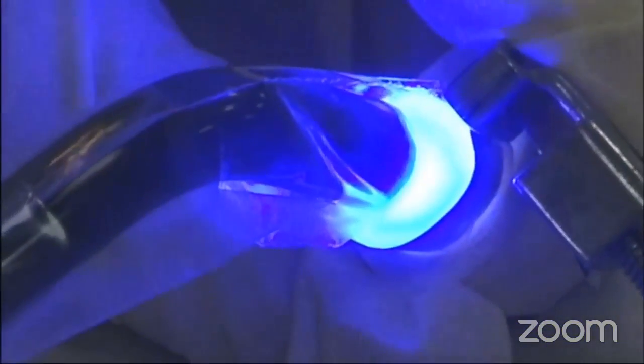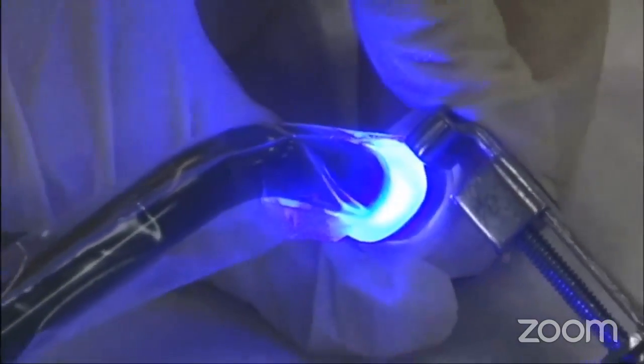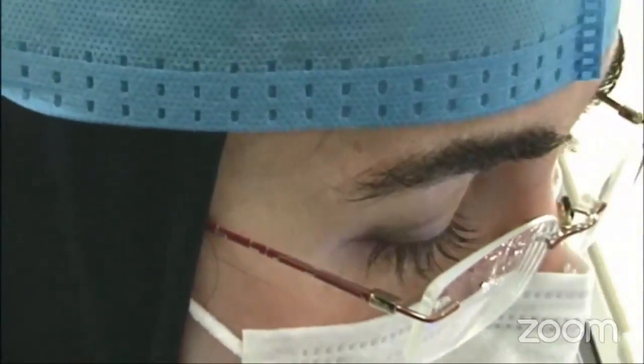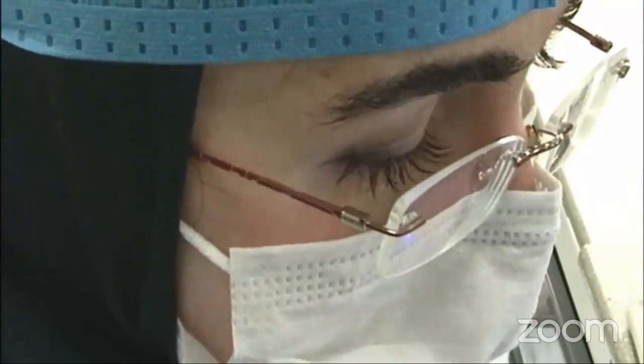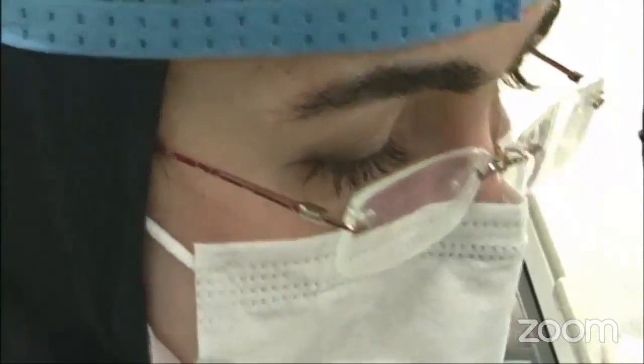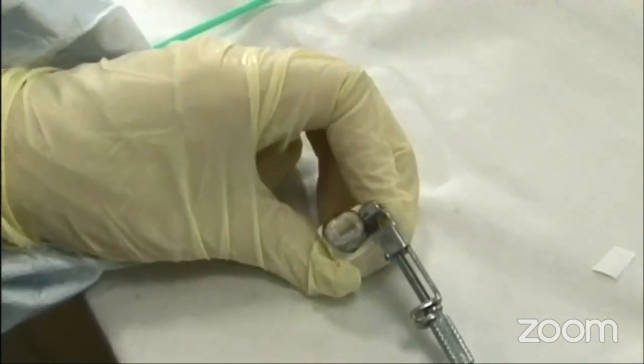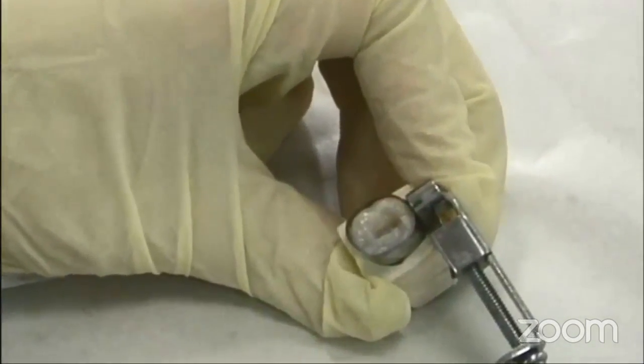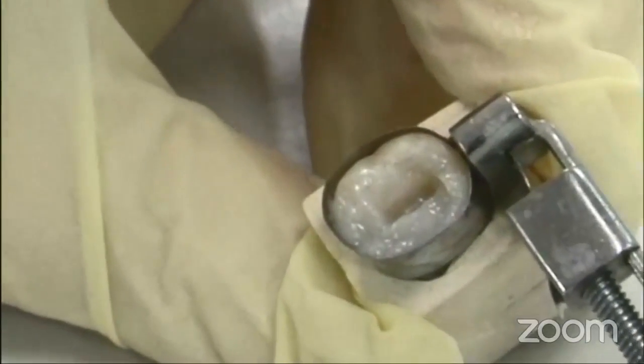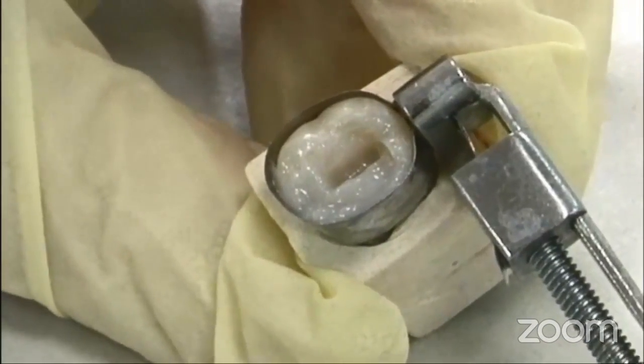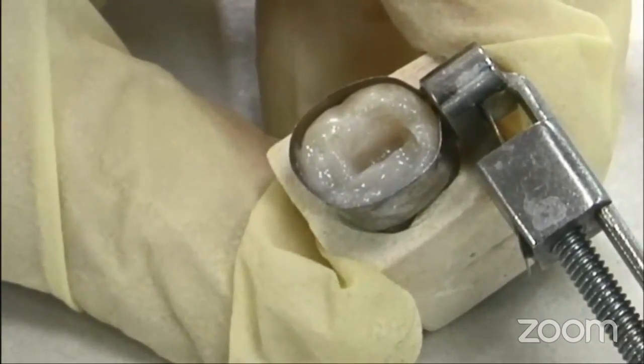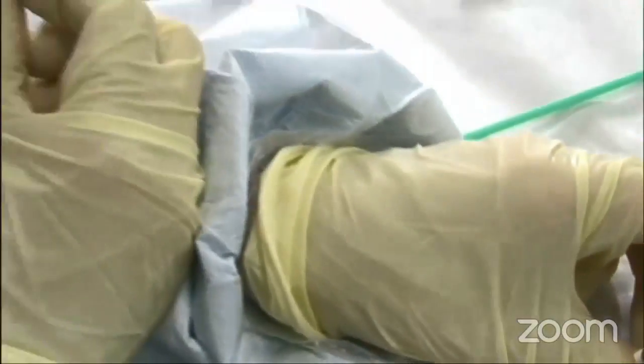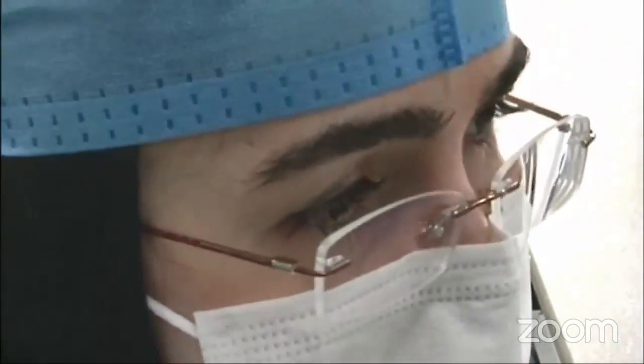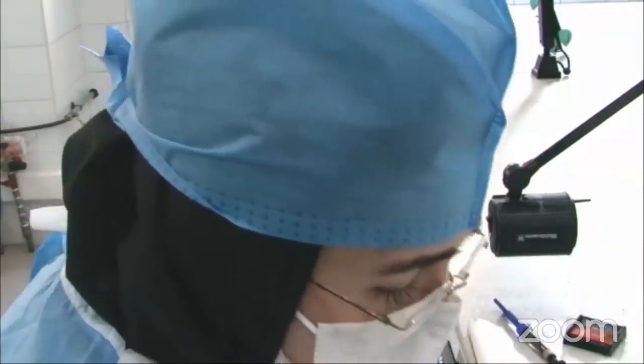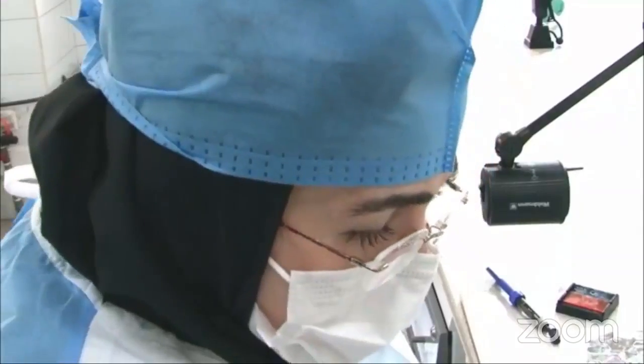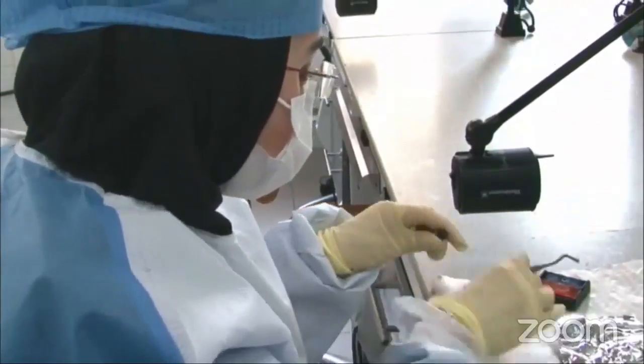One thing I should remind you. As you know, we have two types of fibers. They might be previously impregnated with resin or not pre-impregnated with adhesive resins. The type of fiber used here has been previously impregnated with adhesive resins, so we didn't apply adhesive resin over it. But if you use braided or woven fibers that have not been impregnated with adhesive resin previously, you should apply bonding agent over the fibers, remove the excess adhesive resin, then use it. But as I told you, the fibers I used here have been previously impregnated, so I didn't apply adhesive resin over the fibers again. Now I try to form the occlusal wall with a single layer.